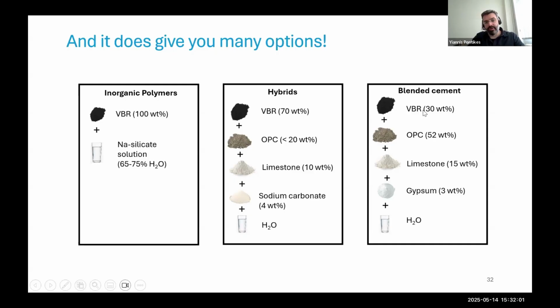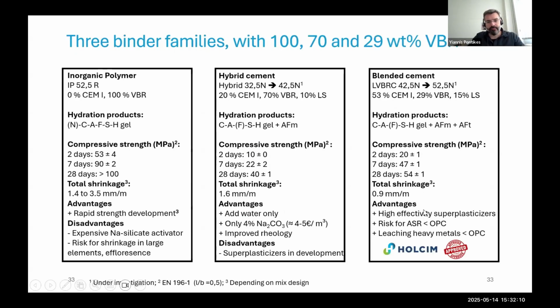And in the third case, you don't have any more alkalis, and the VBR here is less, and that's the blended cement. This is totally business as usual today. Performance changes, varying depending on the mix design. Here you have very, very high performance, also on early-day strength. You can easily exceed 100 megapascal. Here you have good performance, but it's a compromise between performance and environmental impact. This particular family has the lowest environmental impact, and also very good performance. So it is meeting the standards for, in this case, the high-end cement. And we think it's probably the easiest way forward.